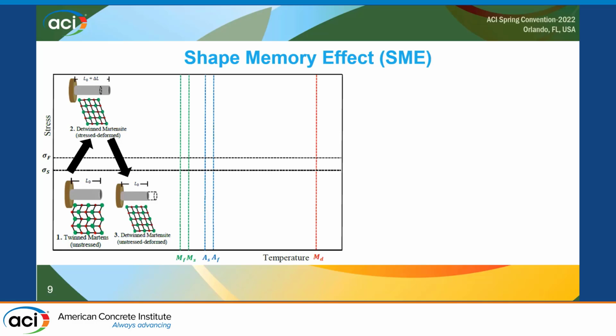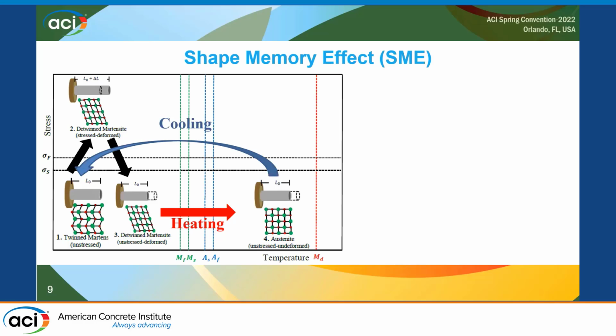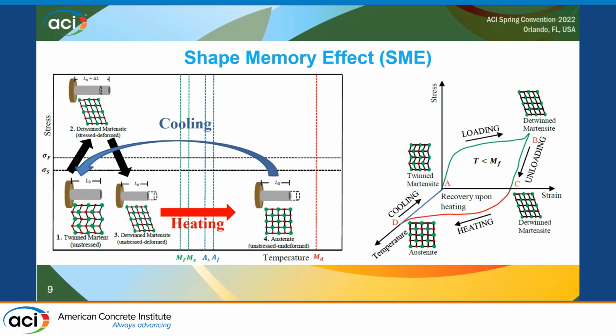Now, what happens when we heat this specimen? It turns into the austenite state, which is the high temperature, low stress state. And when the heat is removed or it is cooled, it goes back to its initial state, that is state number 1, the martensite state. So in this figure, we can see that there is no residual deformation. It has turned into its original position. We can see it from here.